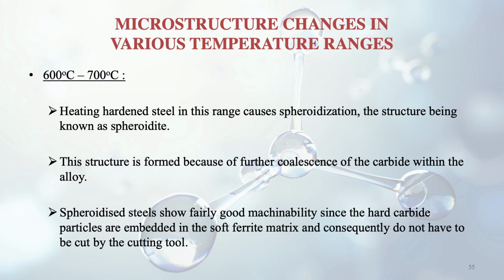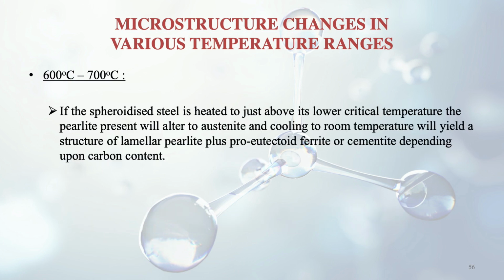If the spheroidized steel is heated to just above its lower critical temperature, what happens then? The pearlite present will alter to austenite, and cooling to room temperature will yield a structure of lamellar pearlite plus proeutectoid ferrite or cementite, depending upon the carbon content. To better understand the lower critical temperature, we have done before, that is 723 degrees centigrade, as you know.